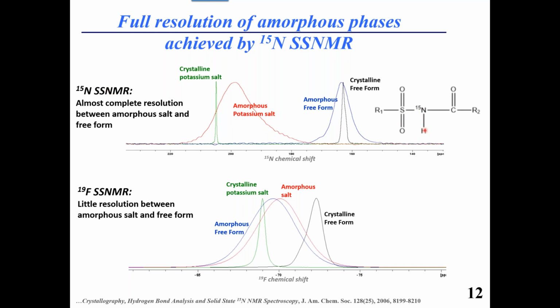Depending on whether you have hydrogen on the nitrogen or have a salt which doesn't have the hydrogen here, the NMR chemical shift changes dramatically. You can clearly see it here. That's how we resolve it. And again, I could point the author of the question to perhaps these papers and others. Obviously, it's not the only paper on N15 solid state NMR out there.